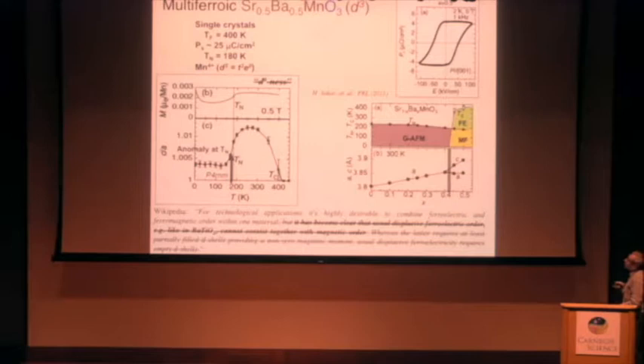Unfortunately, we are not the first to find this multiferroic behavior. Sakai 2011 found them. This is in a pure strontium barium system, at very low temperature measurement of the hysteresis loop. Because materials are leaky with respect to resistive properties, but when they measure lattice constants, they see transition to ferroelectric state and tetragonal structure developed. But when antiferromagnetic transition happens, part of the distortion, sometimes a very large part of distortion, is going away or even may go completely down.